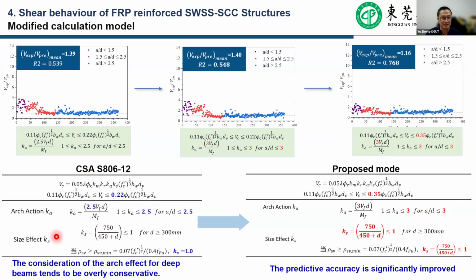First, the size effect should be considered in the whole process, even though the steel ratio is larger than the minimum steel ratio value. And furthermore, the limit value of 2.5 should be modified to 3, and the size effect should be considered even though the effective depth of the concrete beam is larger than 300 millimeters.